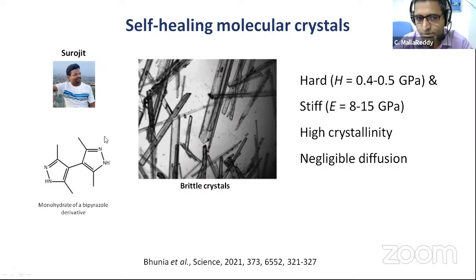This was our idea, to design some particular type of mechanical property in somewhat networked crystals. So we thought of having a kind of three-dimensional network where you have both weak interactions as well as strong interactions. We wanted to see how the crystals would respond in terms of mechanical properties. So my student was looking at these crystals. He found most of these as brittle crystals. These are hard, with 0.4 to 0.5 GPa hardness, and the elastic modulus is 8 to 15 GPa. This is quite high for self-healing materials.